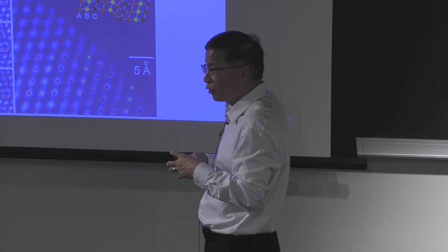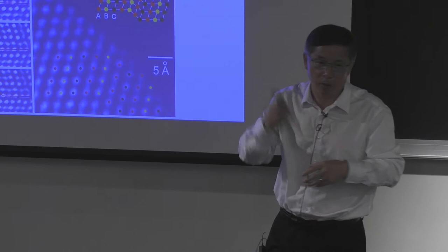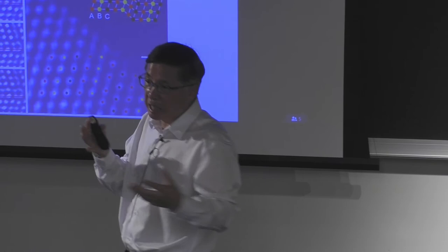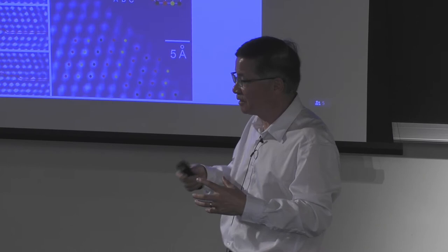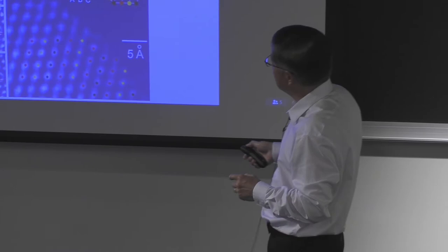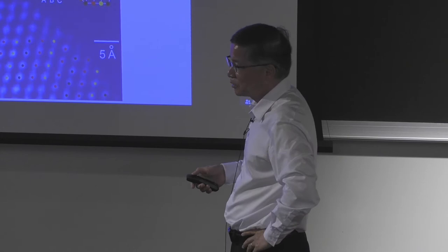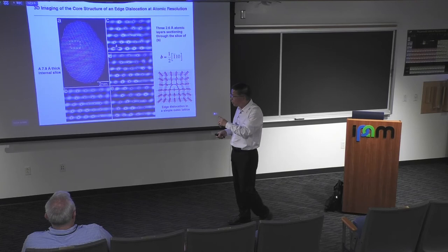Five-fold is very interesting. Paul Voyles, I know, material science has studied five-fold for a long time, because nature doesn't forbid it. And these are twin boundaries, right? A quasi-crystal is defined differently, it's not a twin. The quasi-crystal can have exact five-fold symmetry. But for the twin, at the angle, there's some distortion. If you look at our paper in detail, we have a discussion about the angles, there's some distortions. Okay, then also, the most important for this, yes?